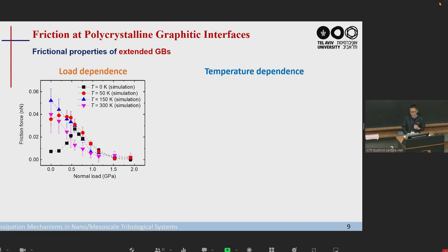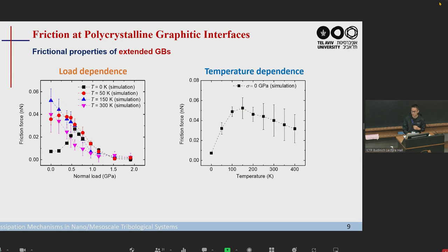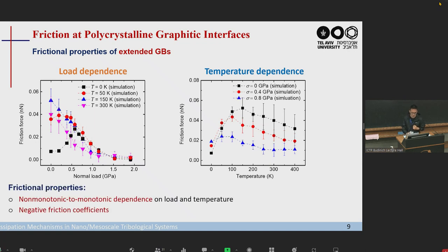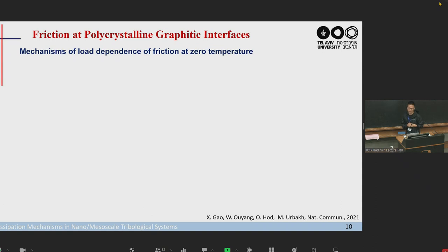And for the temperature dependence of friction, we see somewhat similar behavior. As we increase the external normal load, the peak position changes to lower temperature and finally becomes monotonically decreasing. So also for the load dependence, we see that there is a regime where friction goes down with normal load. This can be defined as a regime with negative friction coefficients and provides a way to suppress energy dissipation for large-scale systems. And then to understand the frictional behaviors, we analyze the energy dissipation properties at zero temperature